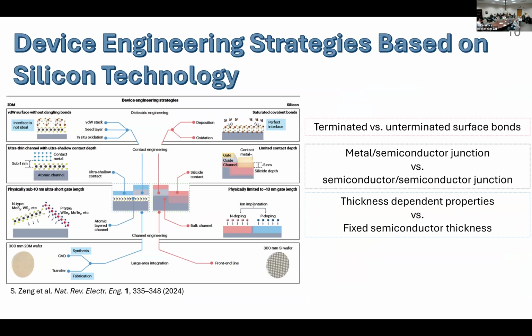And so this gap in the understanding is further complicated by the fact that a lot of the engineering strategies tried to optimize the performance of these 2D field effect transistors are based off silicon technology, despite the fact that there are key structural differences. So for example, in a MOSFET, you have contacts that are made by ion implantation, whereas in our 2D field effect transistor, this is done by directly adding or depositing metal on top of our substrate. So that's going to change the transport properties of the device.